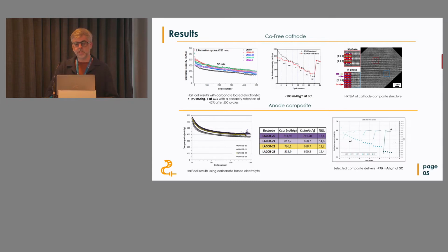Regarding silicon, we are currently using 10% weight of silicon, combined with graphite. We have good cyclability for the recycled silicon, as I mentioned. This is recycled silicon coming from different waste sources, so we are using recycling of photovoltaic panels, for instance, and a lot of treatments to make this silicon active and perform as you can see here, delivering capacity of around 700 on the initial cycles and then down to 400 milliampere hour per gram. And this silicon is also able to deliver capacity up to 3C, which is 475 milliampere hour per gram.